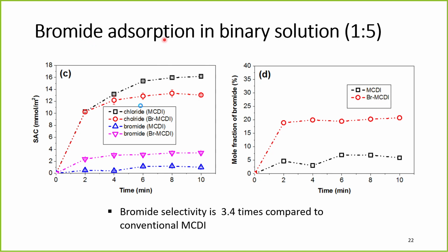The difference between bromide and bromine is that if you oxidize the bromide, you can convert it to bromine. So Br minus converts to Br2, so that you can collect the bromine with chlorination. That's the reason why in seawater it is present as bromide, so we need to first recover this bromide. If you look at chloride and bromide, this is without any bromide-selective component, and this is the bromide MCDI. You can see the normal MCDI is red, and this pink color is the bromide MCDI. Overall bromide selectivity is almost 3.4 times higher than the normal MCDI, so we have increased our bromide selectivity using our bromide MCDI.